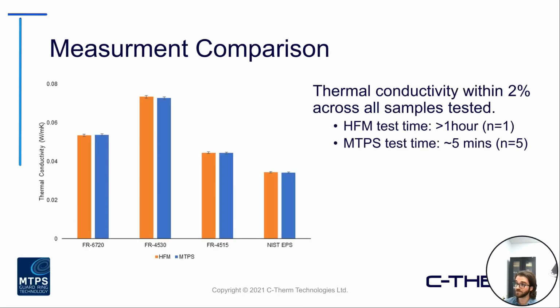Just as an example though, this is some measurement comparisons that were taken on a few different foam insulation samples. We notice here heat flow meter data in orange, MTPS data in blue. Across all tested samples, again, see a couple various foams and then the NIST EPS standard, thermal conductivities were well within 2% of each other.